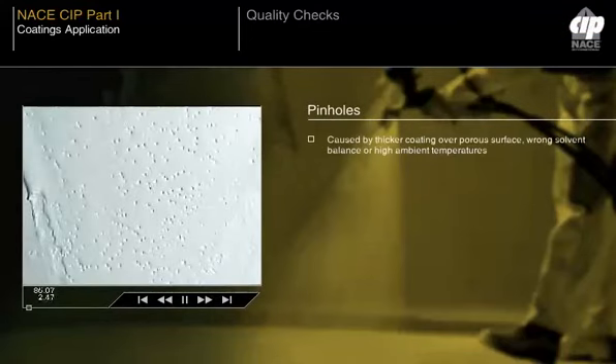Pinholes are small visible holes in a coating, often caused by application of a thicker organic coating over a porous surface. For example, coating epoxy over concrete or over inorganic zinc. Coatings with the wrong solvent balance may also suffer pinholing, caused by the inability of solvent to escape from the rapidly curing coating.